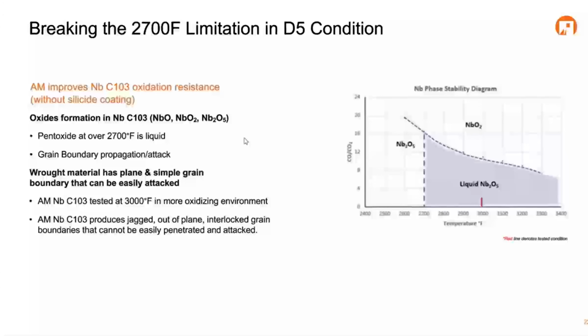One of the challenges of refractories, especially niobium-based alloys, is they readily oxidize. It just so happens that the niobium pentoxide that can form has a melting temperature quite a bit less than the base material itself, all the way down at 2700 degrees Fahrenheit, when many of our applications are potentially at 3000 degrees F or more.